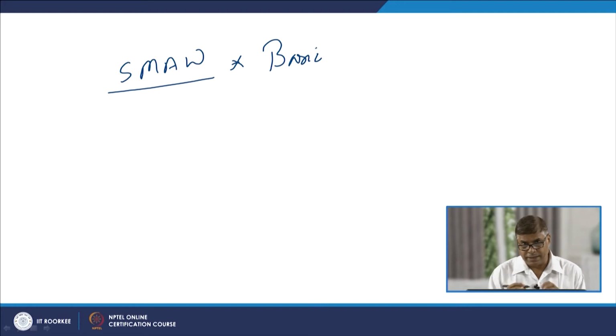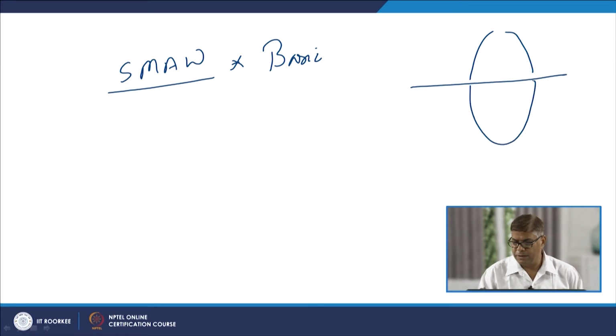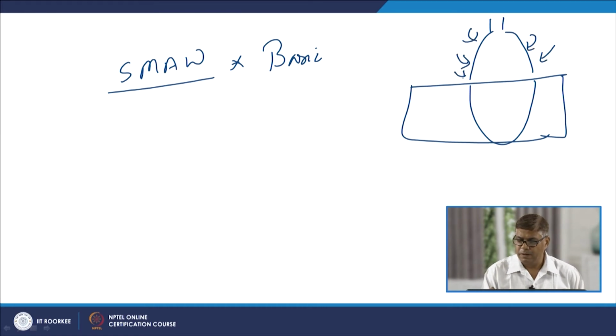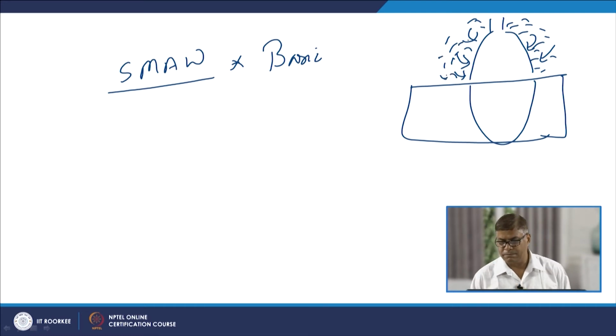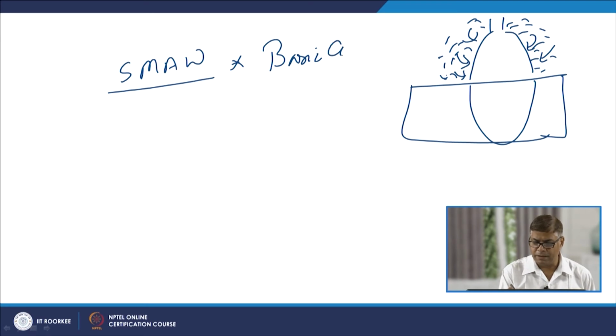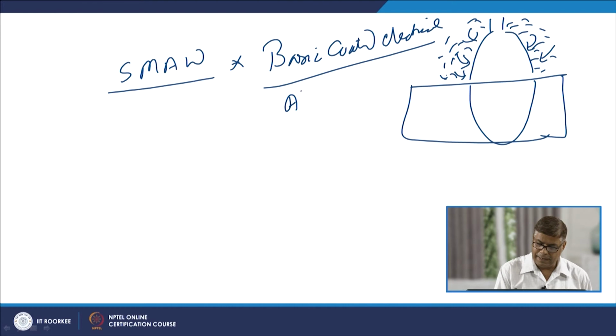we know that the protection of the weld pool from the atmospheric gases is very less. The protection of the molten pool in case of the SMAW process is poor, because whatever inactive gases are produced, they are produced through the thermal decomposition of the coatings available in the flux, and they provide a loose shroud of inactive protecting gases around the arc as well as the molten pool, and therefore protection is poor. So, in order to provide effective protection, basic coated electrodes are used for the welding of the aluminized steels by the SMAW process.